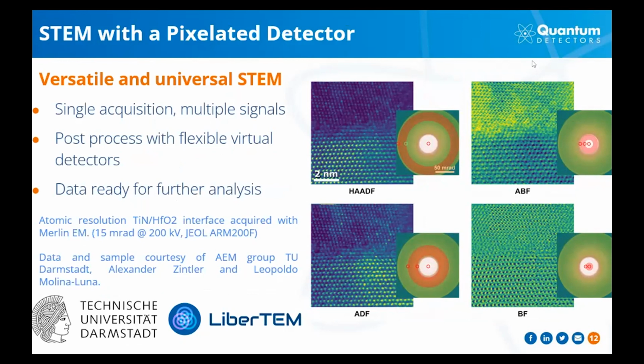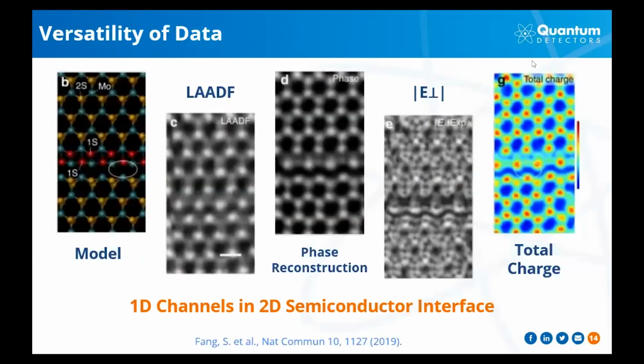So I worked with Alex to get the data of this sample, a titanium nitride and hafnium oxide interface, and I plotted the standard signals here, which are done by summing the particular angular ranges from the 4D STEM data. The important point I would like to make is that this analysis can be considered just a starting point. Once 4D STEM data like this is collected, it can be analyzed by more advanced algorithms like ptychography. We can look at symmetry breaking in this data. We can cross-correlate the beam positions and so on. So let's now have a look at what additional information we can get out of the 4D STEM detector.